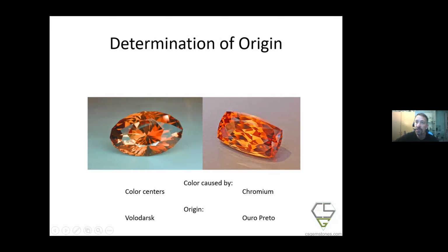So if we measure the chemistry with this laser ablation, we will find that here we have chromium as the source for the color, and here we have color centers. There is no chromium. And we can assign the origin here as being from Volodarsk or Koroshiv, and this one is Ouro Preto. So this is a lot of money, still very good color, an attractively colored specimen, but you are not sure if the color is stable. At the moment, I can say it's at least stable for 5, 6 years, as long as that's the time that I have had it in my collection. But Pakistani material that is irradiated might have almost the same color, and that will fade within a couple of weeks or months.